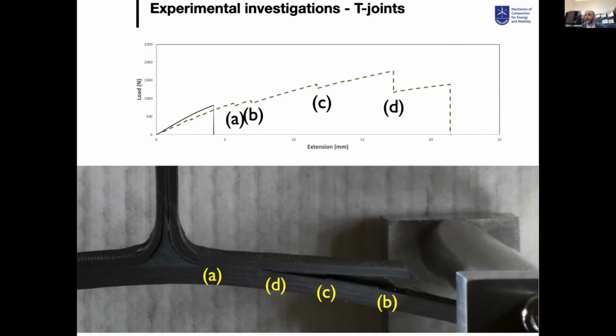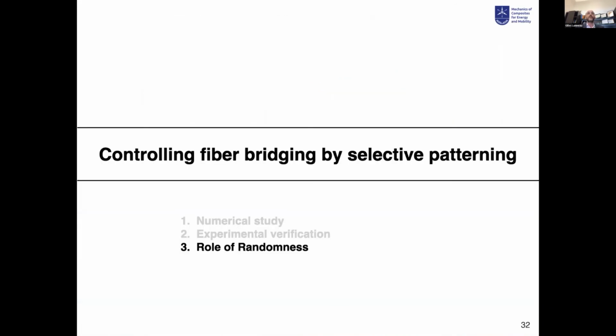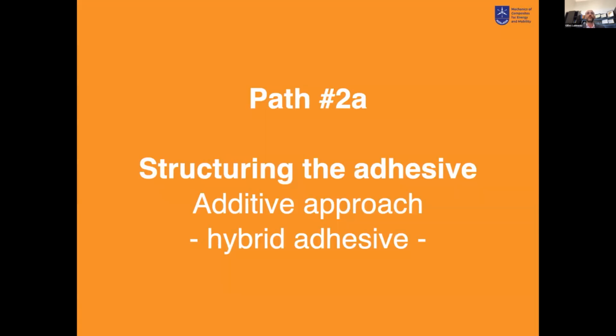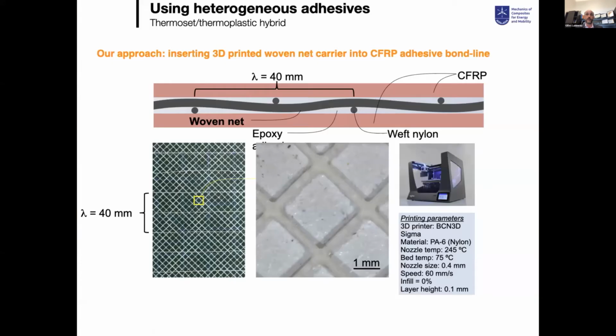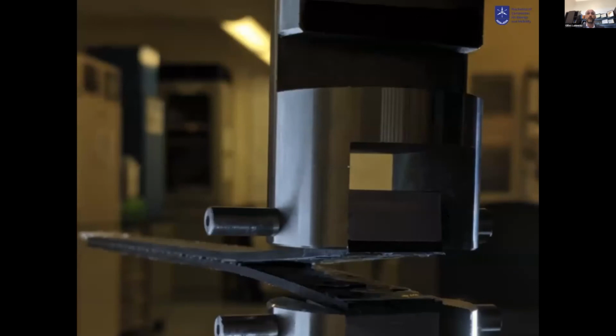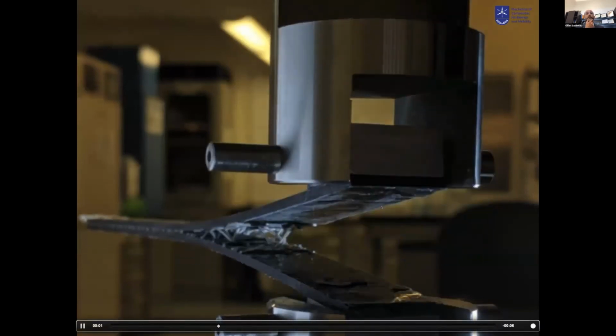There is a second technique that we developed that is now structuring the adhesive itself. So structuring the adhesive for us is based on making sure that the adhesive layer that is going to break is going to dissipate as much energy as possible during the delamination. And this we do by introducing a hybrid adhesive bond line between the substrates. So that means we introduce thermoset and thermoplastic composites together. And if you engineer this completely correctly, what you get in terms of delamination is something that looks like this.